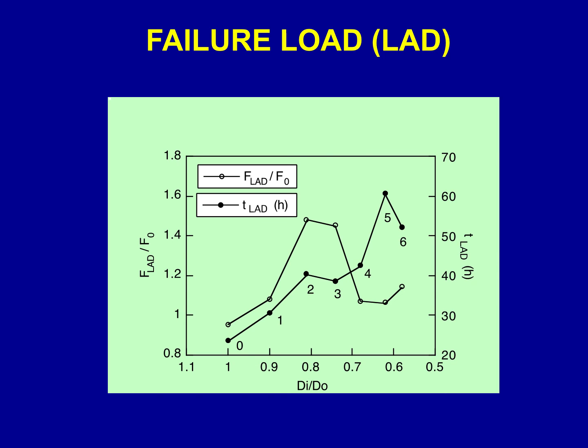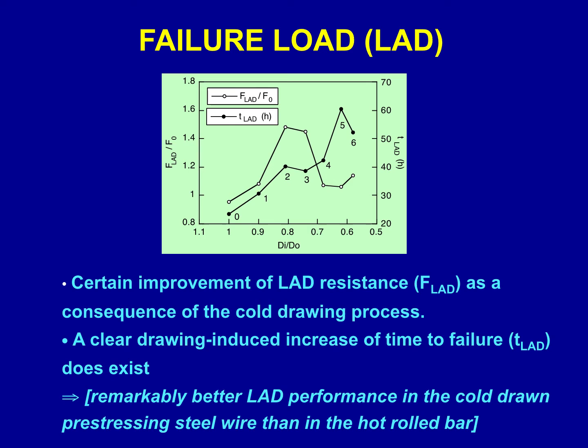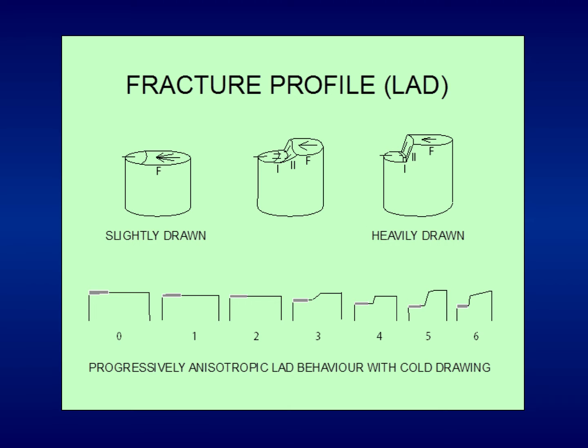Then we can observe a certain improvement of localized anodic dissolution resistance, F_LAD, as a consequence of the cold drawing process. There is an increase, a clear drawing-induced increase of time to failure, t_LAD, does exist. It implies a remarkably better localized anodic dissolution, stress corrosion cracking performance in the cold drawn pre-stressing steel wire than in the previous hot rolled bar based material.